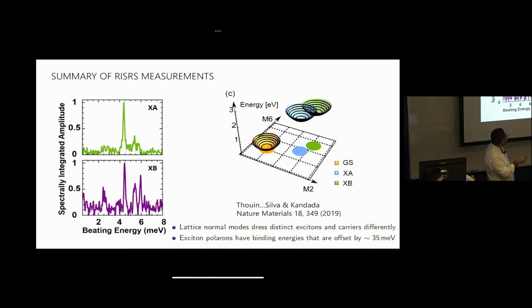We have a ground state. We have different excitons here, XA and XB, that are coupled differently to two different phonon modes here in this representation. These axes are like a displacement axis along some effective coordinate for each of these phonons. It's, let's say, project all of the motion into a single coordinate, and you would have these different plots.